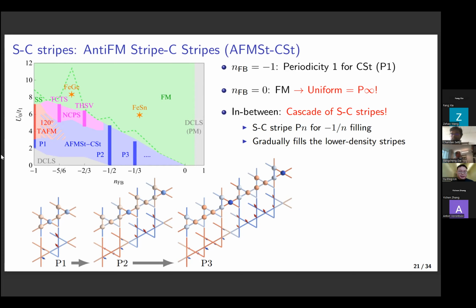Yeah, that's a very good point. So at least from our theoretical analysis, if you only have on-site repulsion, then the lower density site will be completely non-magnetic. But if you introduce the extended repulsion, then generally this site could be magnetic also, but it will have a much weaker magnetic order than the higher density sites. Okay. Yeah, and I expect this to be experimentally relevant.